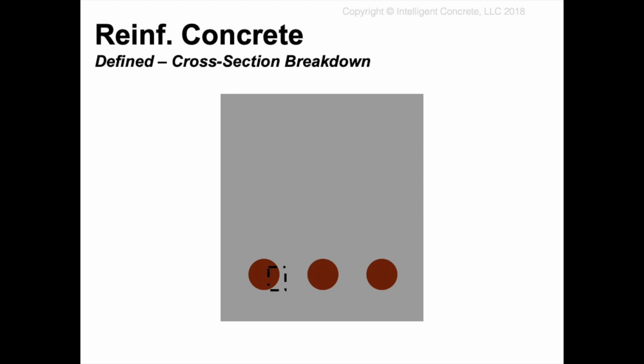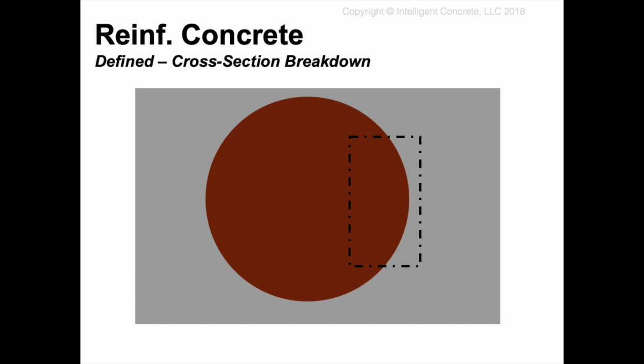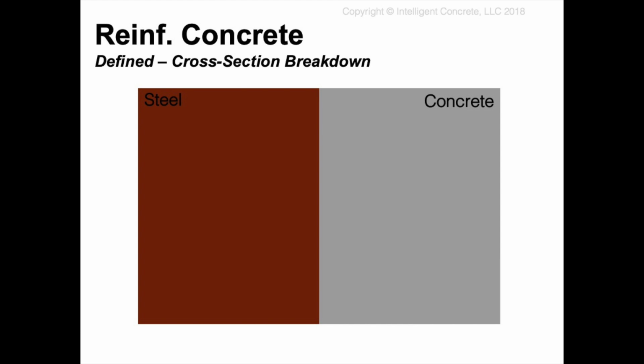What we've done here is we've taken that cross section, and we're examining the reinforcing steel interface. The gray is the concrete and the brown is going to be our steel. I'm going to zoom into it here. And zooming in even more, what we find is not only do we have that interaction between the steel and the concrete, the interface, but at that interface we're also going to have other things like water and contaminants that are in that pore water solution.